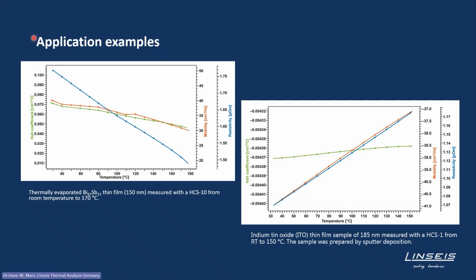So let's have a look at a couple of application examples. The first measurement shown here on the left was done with the HCS 10, so with an electromagnet. A sample of bismuth antimonide was analyzed. It was a thin film of 150 nanometer thickness, which was thermally evaporated. The measurement was done from room temperature up to 170 degrees centigrade. You can find here in green the Hall coefficient, in blue the electric resistivity, and in red the mobility, which is calculated from the Hall coefficient and the resistivity.